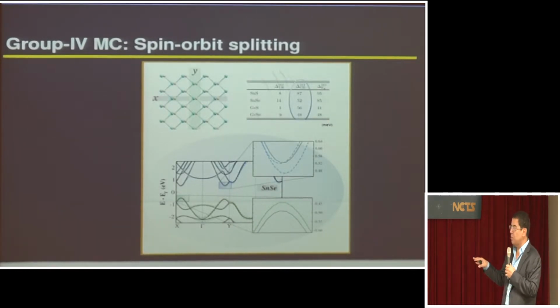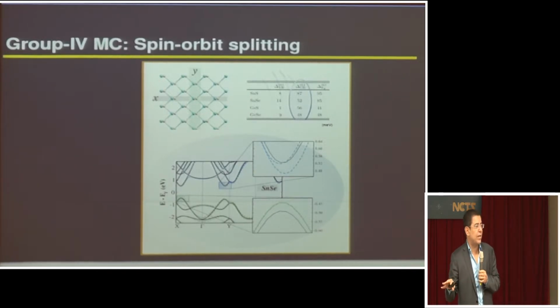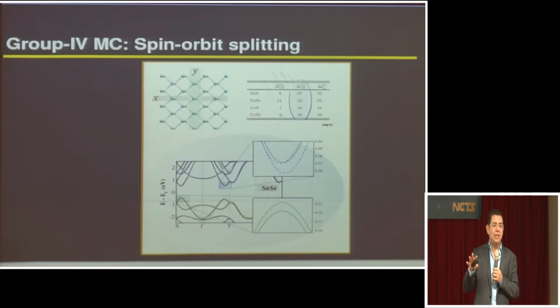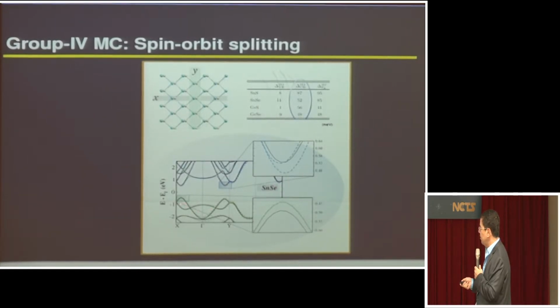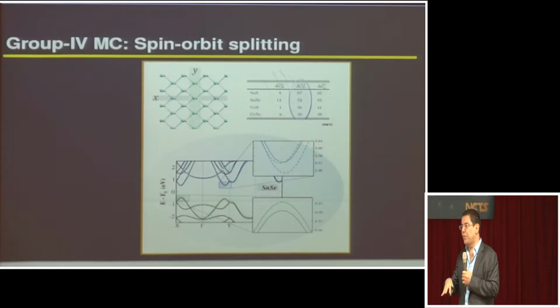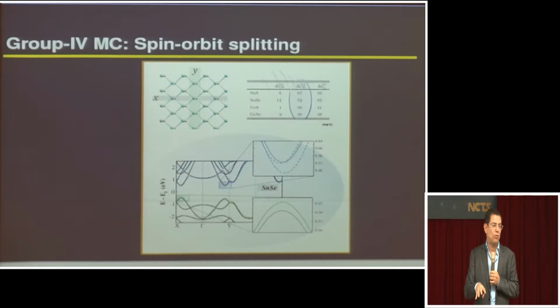An interesting thing about these monochalcogenides is that, just like in the case of gallium arsenide, for instance, you have spin-orbit coupling. And spin-orbit coupling is very interesting, of course, for many things, including spintronics. Okay? And this is an example, for instance, of tin selenide. The interesting thing is that tin selenide is an indirect band gap semiconductor. And what you see is that the spin-orbit coupling affects the conduction band very strongly. So people who work in traditional 3D semiconductors know that usually the effect of spin-orbit coupling is in the valence band. Okay? In these materials, actually the effect is in the conduction band.